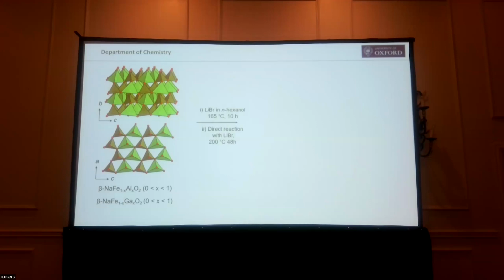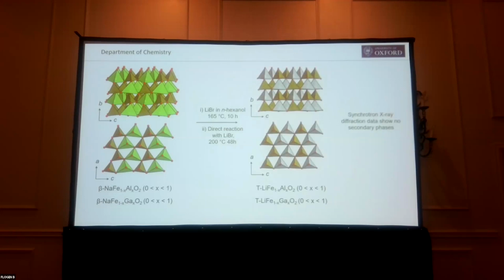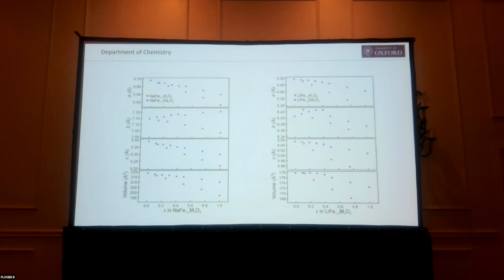We do the cation exchange in a slightly different way, but we can get it complete in a repeated recipe. So we get about 90% exchange at this level, but we then treat the material with solid lithium bromide rather than a suspension, and that gives us a good conversion. And what we can then do is make the equivalent substituted lithium phase. What I'm showing you here are the lattice parameters of the solid solutions. Here are the sodium phases that we make with and without the gallium, and here are the lithium phases once we've done this substitution.